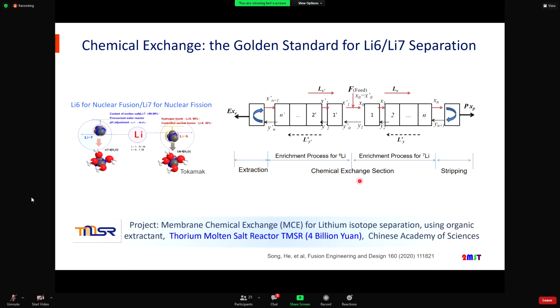If you look at the separation technology, a large part of this process is chemical exchange. We have extraction and stripping—extraction is putting the lithium into the system, stripping takes the lithium out of the system. We have cascade processes, where each step is a single-stage separation. So we put hundreds of cascade separation stages together, and when we reach equilibrium, we can produce pure lithium-6 or pure lithium-7.